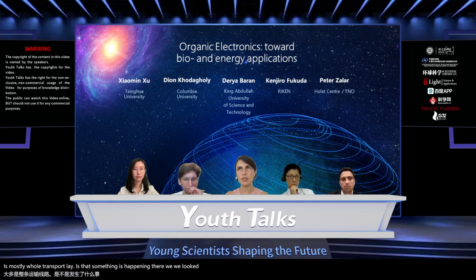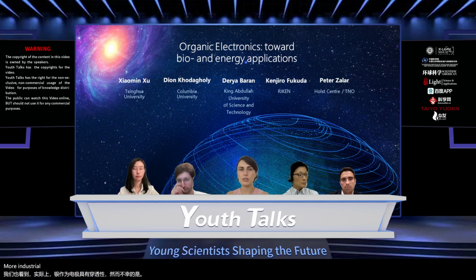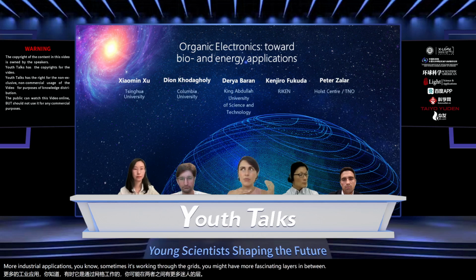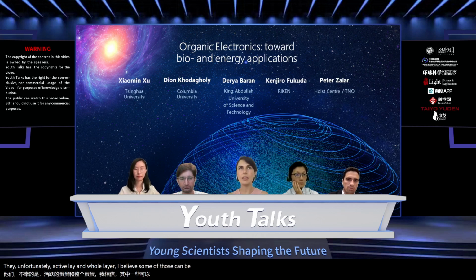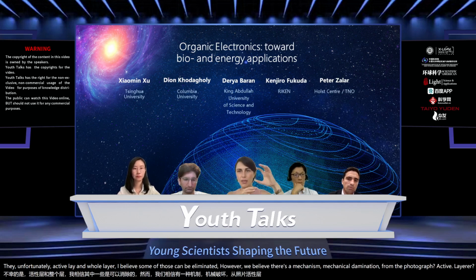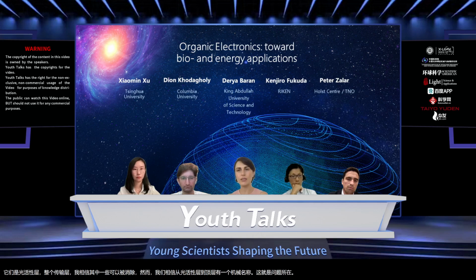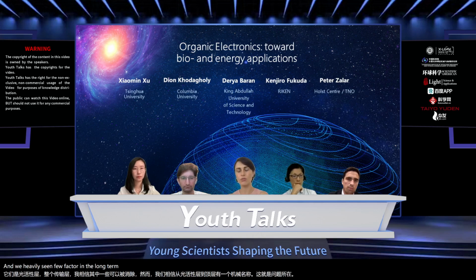We looked into things like the surface recombination increasing over time. We have also seen that the silver electrode has penetration, unfortunately. However, thinking about more industrial applications, sometimes it's working through the grid. You might have more passivating layers in between the photoactive layer and the hole transport layer. I believe some of those can be eliminated. However, we believe there's mechanical delamination from the photoactive layer to the top layer, which is the problem, and that we heavily see in the fill factor in the long-term stability.